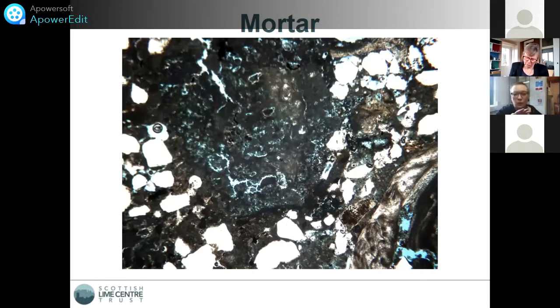Now, the lime that we had here was a non-hydraulic to possibly feebly hydraulic lime. And the reason that I know that is by looking at the lime inclusions and looking for something called clinker components. So when you burn a limestone that has impurities, you form silicates and aluminates in the mortar, which impart the hydraulicity to the material. But all of these clinker components were concentrated within the lime inclusions.